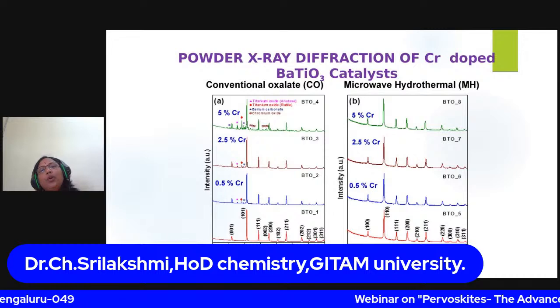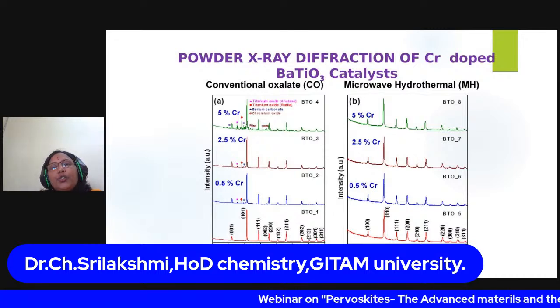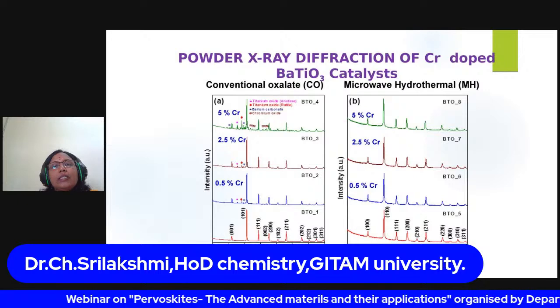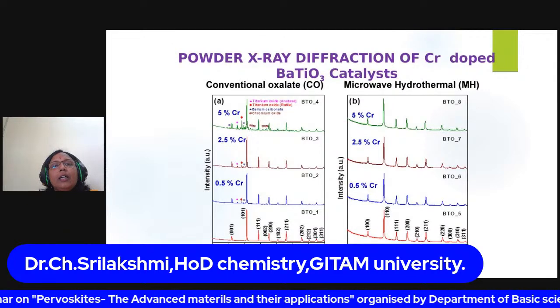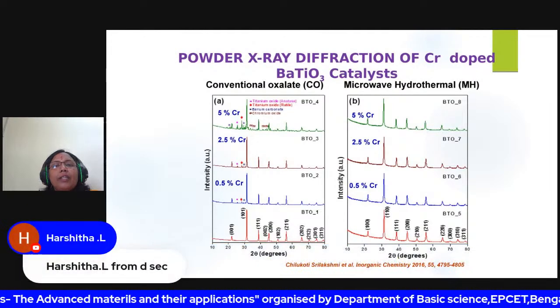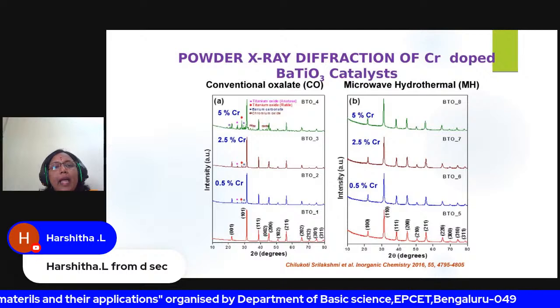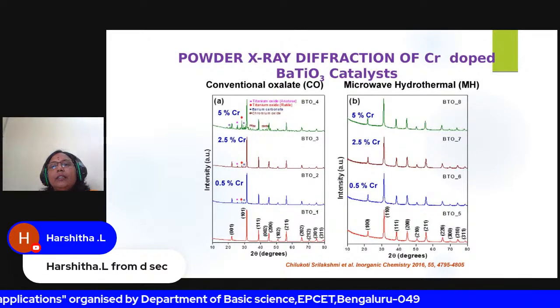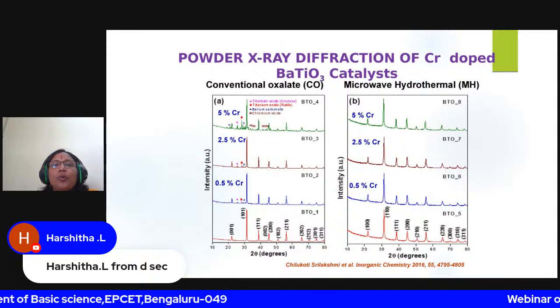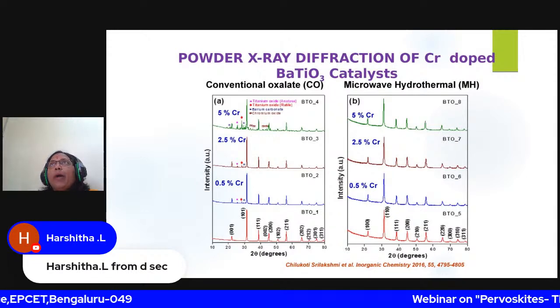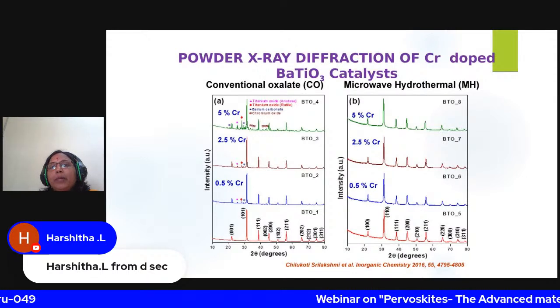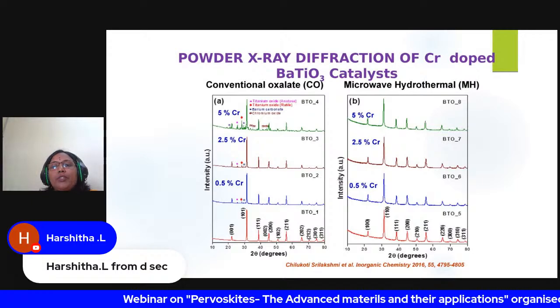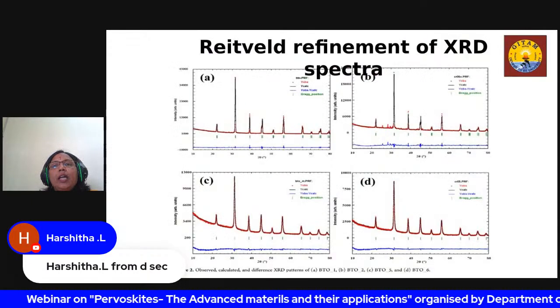So now you can see what is the difference between these two samples here. In the CO synthesized samples, you can see the presence of secondary phases, whereas these are absent here. It means that one can synthesize the pure compounds by using the microwave hydrothermal synthesis method. Okay. So these results are published in Inorganic Chemistry in 2016.